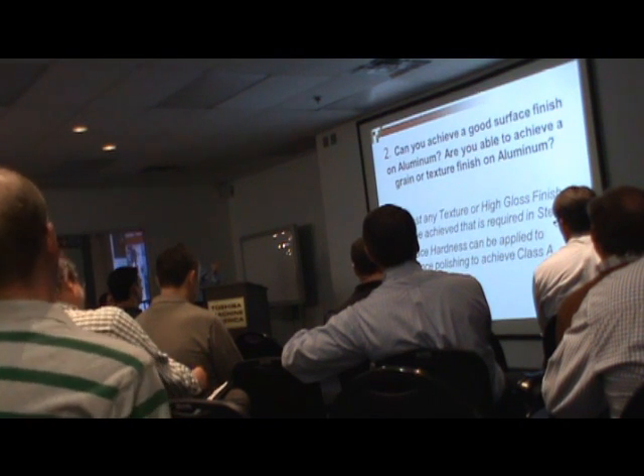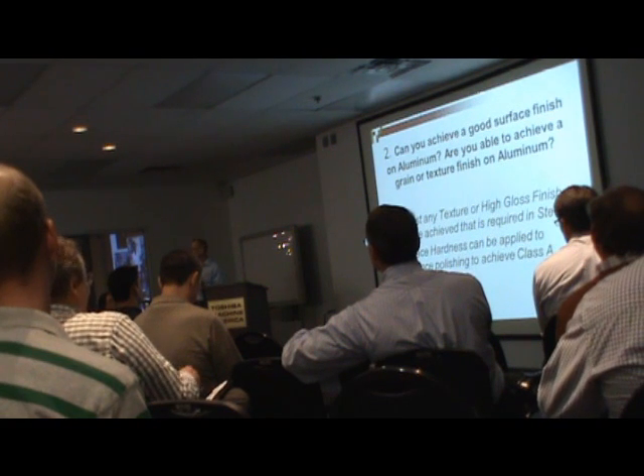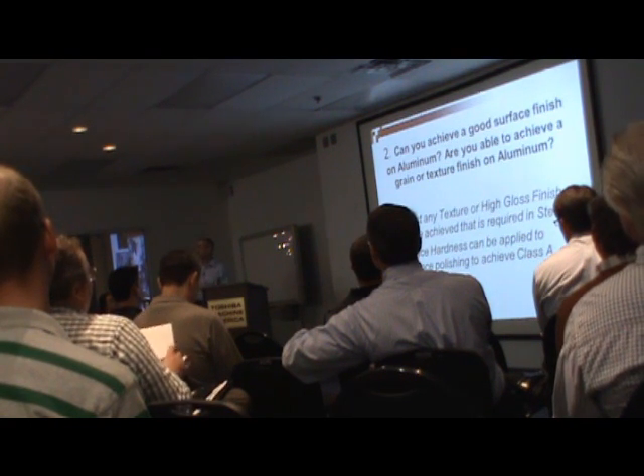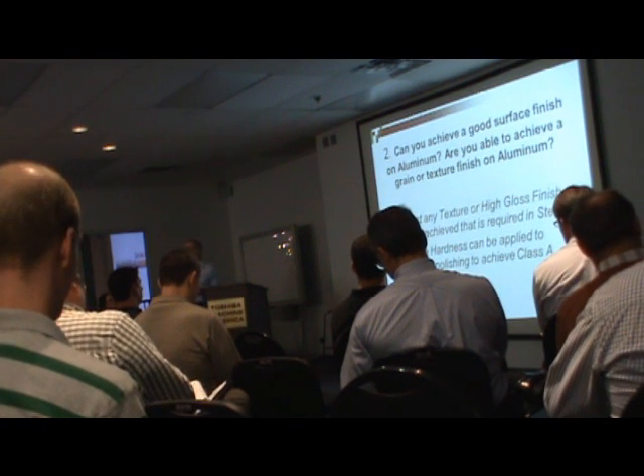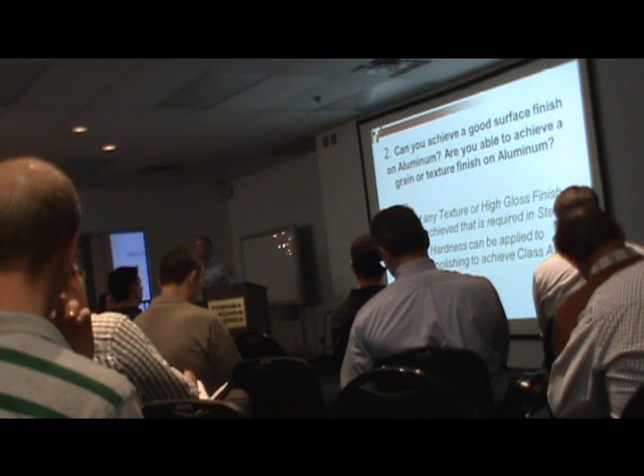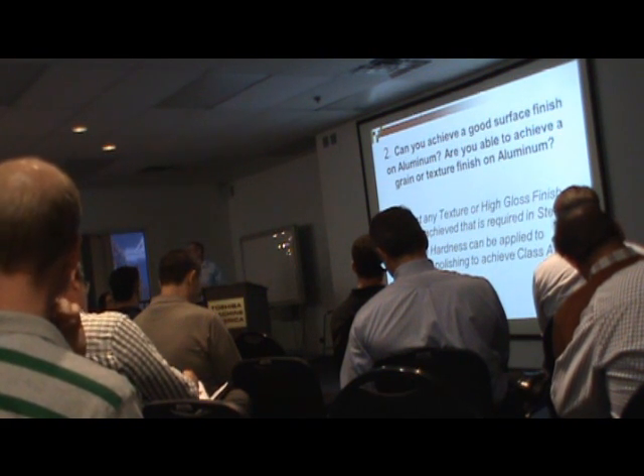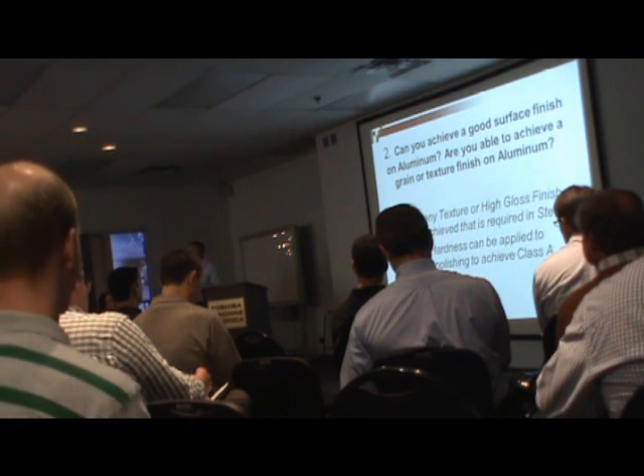As far as the surface hardness, the reason we like to use that is, if we bring it up to a Class A, they use that for the final, what looks like a chrome plating. We use what's called NIBOR, and we use a company out of Chicago called Bales that specializes in this, which helps bring it up to a Class A surface. We actually have some examples downstairs. You're able to see a Class A surface in aluminum, and the tool that's running in the press today has a Class A surface.